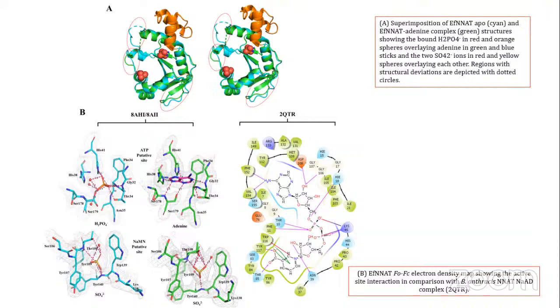Also, another important thing to note about the structure is that these ions, even though they are not the natural substrates of the enzyme, were of great value in that we were able to assess the binding site, because the sites they occupied were the putative binding sites for ATP and also for NAMN. The superimposition of these two structures shows that adenine and the phosphate ion bind at the same site, while the sulfate ion, which is found in the two different structures, occupies the same site.